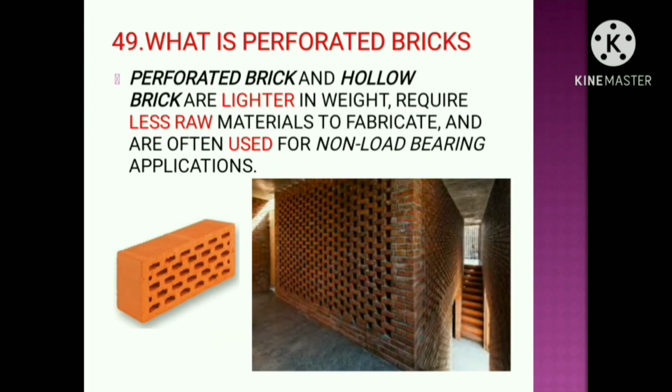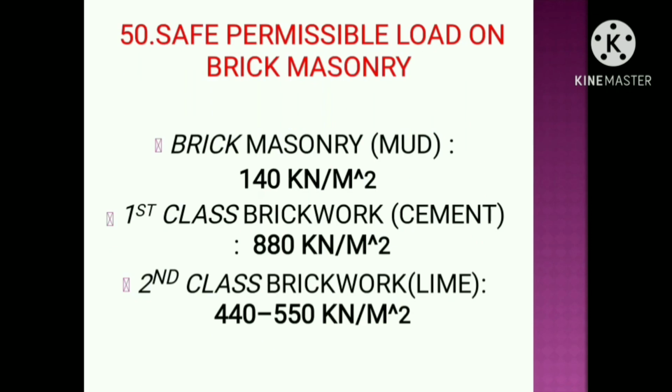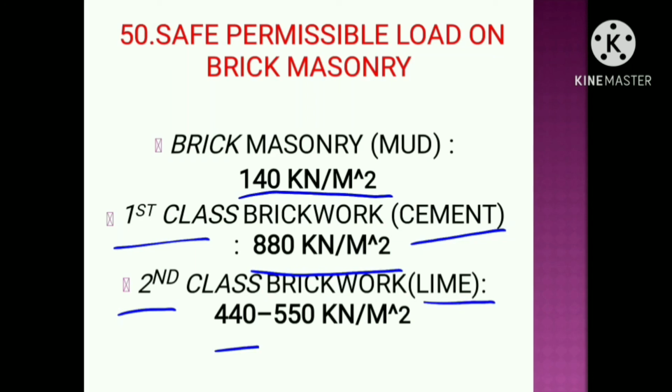What are perforated bricks? Perforated bricks or hollow bricks are almost the same, and these are lighter in weight, require less raw material to fabricate, and are used for non-load bearing applications. Safe permissible loads on brick masonry: brick masonry of mud can take a load of 140 kN per square meter. First class brickwork of cement can take 880 kN per square meter, and second class brickwork of lime can take 440 to 550 kN per square meter.